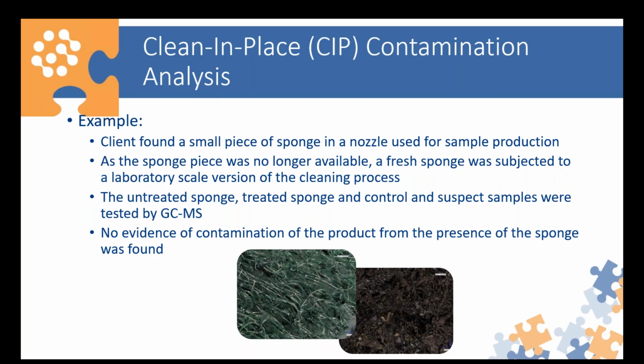And so what we did, as the original piece was no longer available, we obtained a fresh sponge of the same sponge that they were using, and we subjected that to a laboratory scale version of the cleaning process. The same chemicals, times, and temperatures as close as we could mimic in a laboratory scale in order to see the impact on the sponge.